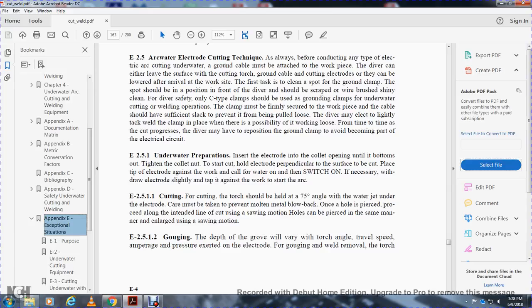2.5.1.1 Cutting. For cutting, the torch should be held at a 75-degree angle with the water jet under the electrode. Care must be taken to prevent molten metal blowback. Once a hole is pierced, proceed along the intended line of the cut using a sawing motion. Holes can be pierced in the same manner and enlarged using a sawing motion.